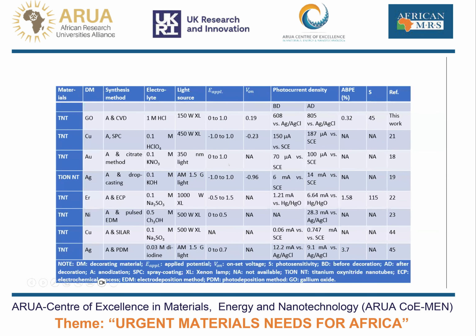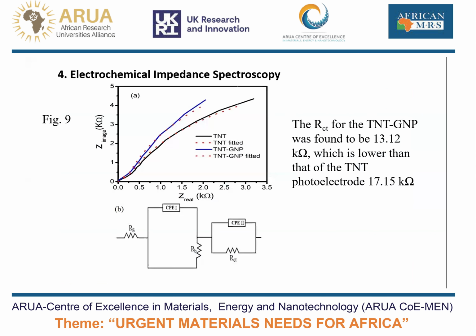We compare our result with other related works in the literature. As can be seen in this table, our material has performed reasonably as compared to other passivated or surface modified titanium oxide nanotubes for water splitting. As I said, this is the first time titanium oxide nanotube is decorated with gallium oxide, and they're showing reasonable performance, proving that gallium oxide is suitable to improve the efficiency of titanium oxide towards water splitting and for photodegradation.